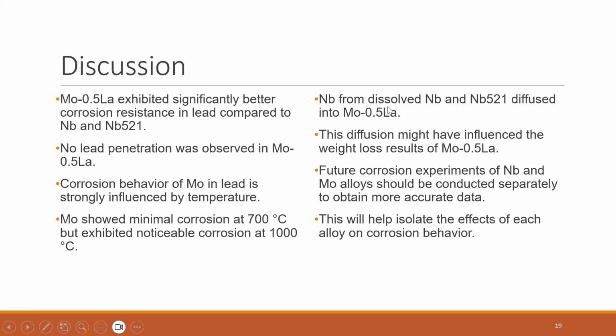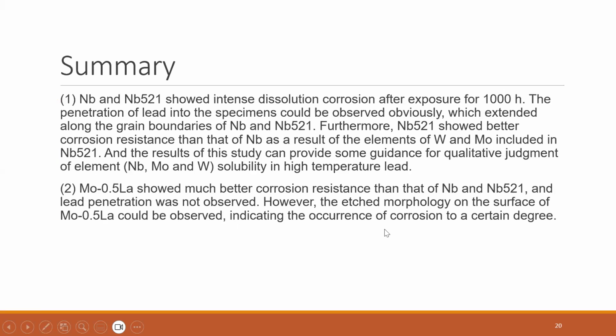And niobium from niobium and niobium alloys diffused into molybdenum alloy. The diffusion might have influenced the weight loss result of molybdenum alloy. Further corrosion experiments of niobium and molybdenum alloy should be conducted separately to obtain more accurate data. This will help isolate the effects of each alloy on corrosion behavior.